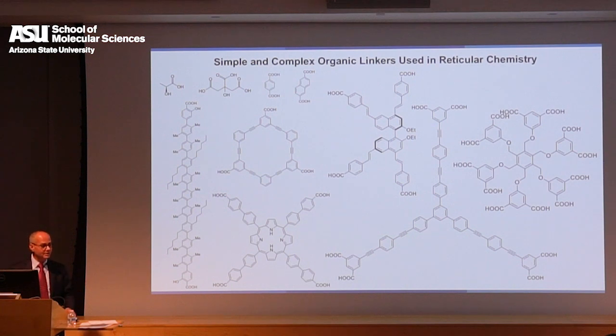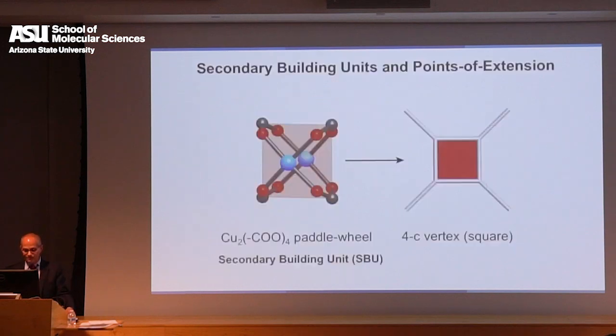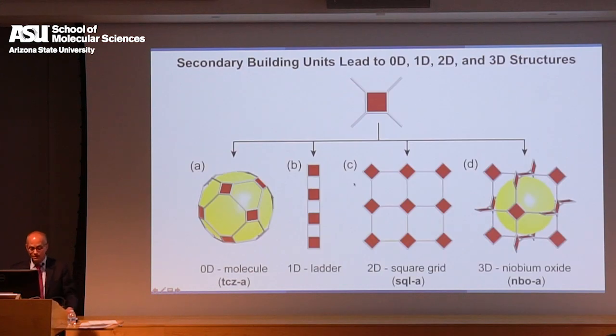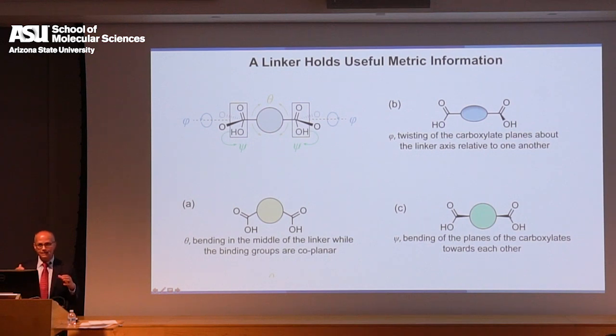Remember, these MOFs are structures that people said could not be crystallized. And so you can imagine the excitement in the field. So like I said, with Mike's thinking about using the building units as geometric objects, we were able to, these are Mike's drawings actually, take squares with the proper organic linker that can put these squares at the required angles, and we could make zero-dimensional structures, chains, ladders, square grids, and three-dimensional structures. So all of a sudden, a linker like terephthalate became a conveyor of geometric information so that you can make the MOF that you desire.